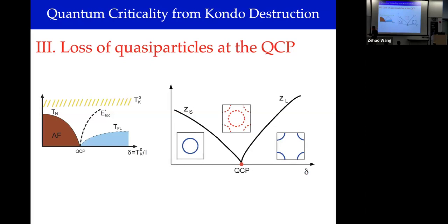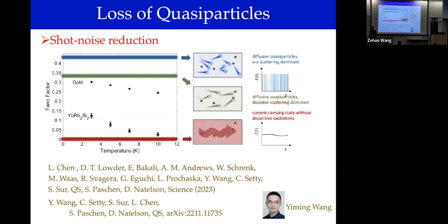At some stage, we worked with experimentalists on the Wiedemann-Franz ratio measurement, the thermal conductivity to the electrical conductivity ratio, that provides 10% evidence for violation of that. So it was an indication that quasi-particles are lost, but 10% evidence was not considered strong enough, at least by some in the community.